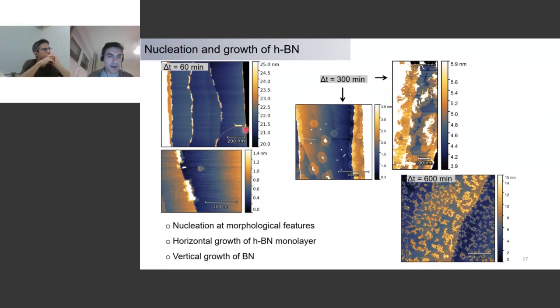Wrinkles form in graphene, for instance, when you cool down the sample, the silicon carbide sample, quite fast. Due to the thermal expansion of graphene and silicon carbide being quite different, you end up having this deformation of wrinkles at the surface. And that's where we see that some material is nucleating, which we assume to be boron nitride. So you can see these tiny islands here.